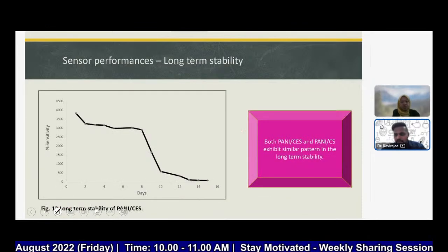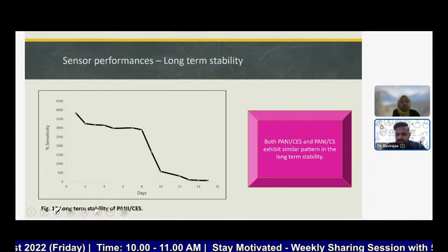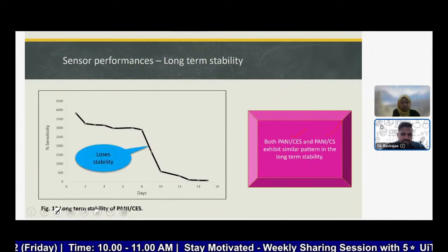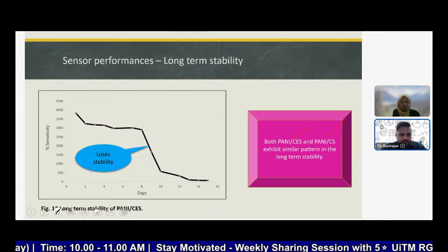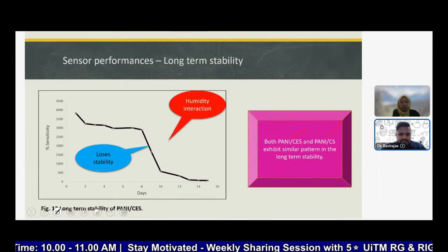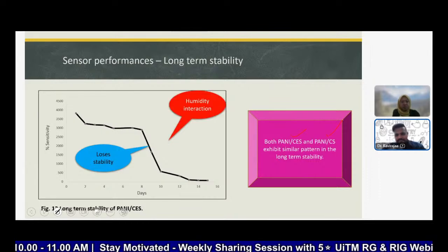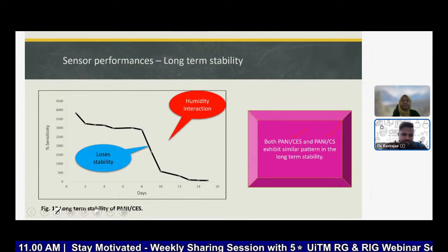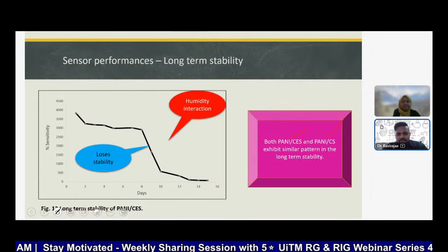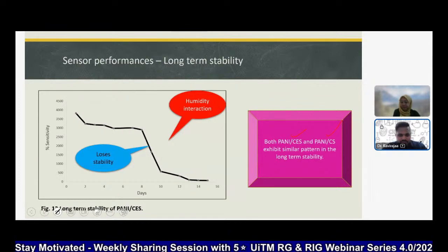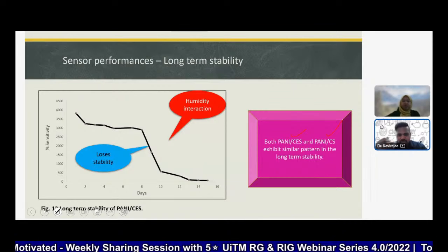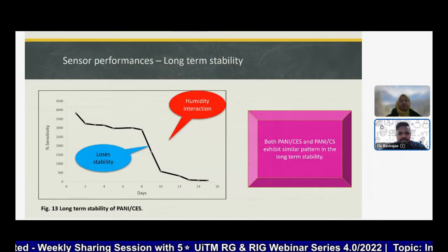So for the chicken eggshells and crab shells, we found the stability somewhere up to 8 days. And after that, probably because every time we have to take it out and then put it back into our container and so on, maybe there might be some humidity interaction, which causes it to lose some sensitivity.